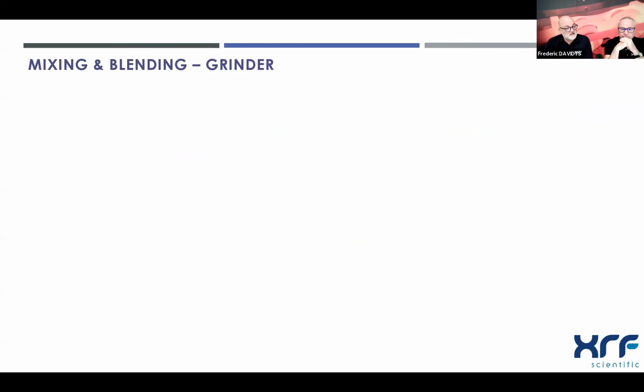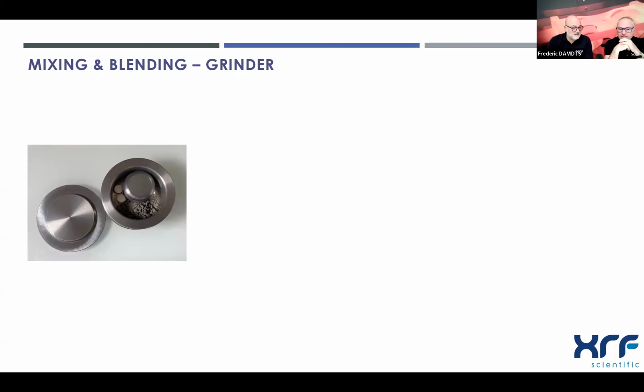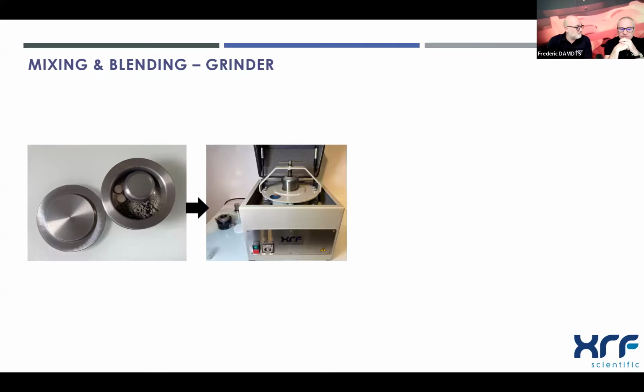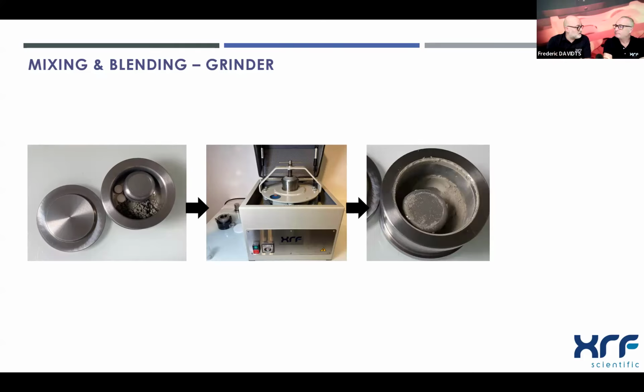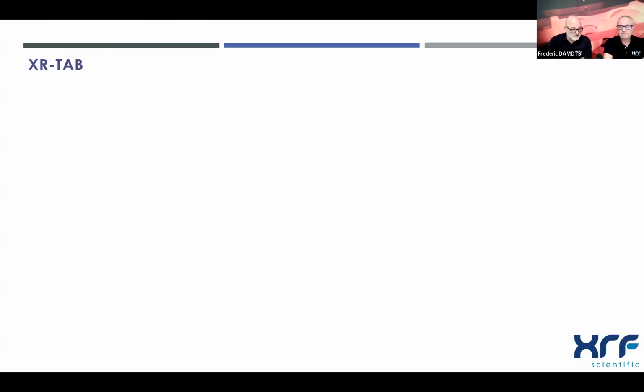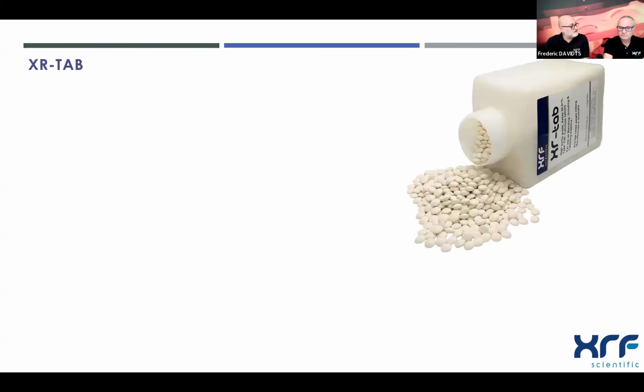Now we can do mixing and blending using a grinder. In that case, the binding agent is added directly before the grinding and mixed during the grinding process with the sample to obtain a homogeneous powder and, of course, perfectly homogeneous pellets of the powder. And for that, we use most often cellulose and XR-Tab tablets.